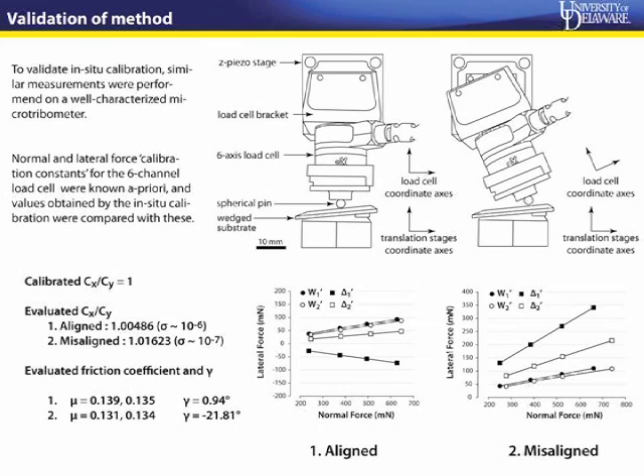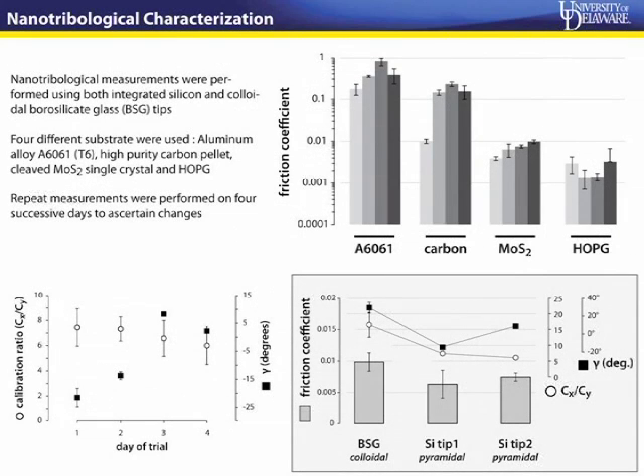With these numbers, how close the CxCy values are to what they should be, and the repeatability of the friction coefficient values, this tells us that this method really works. So the next logical step is to apply it to a nanotribological system. One of the first tests that we did was scanning 4 different substrates. This was aluminum alloy 6061 with a T6 treatment. We had a high purity carbon sample, MoS2 single crystal and HOPG. MoS2 and HOPG were both cleaved samples.